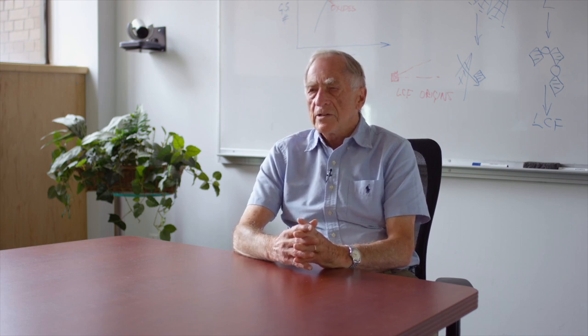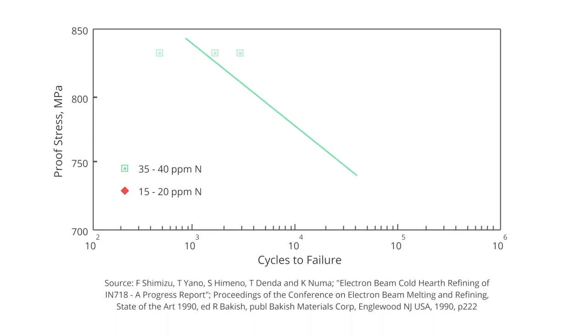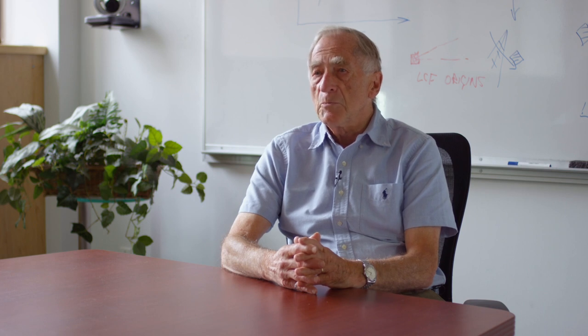The main factor is that we don't alter the fundamental properties of the alloy itself, but what we do is make the properties more predictable and reliable. So if we look at the LCF values that we obtain in high nitrogen alloys, normal nitrogen alloys, and low nitrogen alloys, what we see is that the LCF values are closed in. And for the very low nitrogen content, what we find is a rather narrow dispersion of LCF values. In aerospace terms, that means the three sigma has been considerably reduced, which makes the property in engineering design much more predictable.